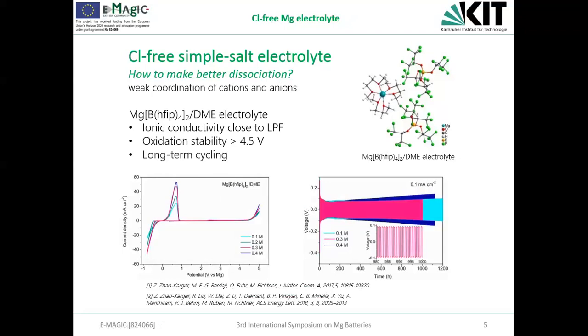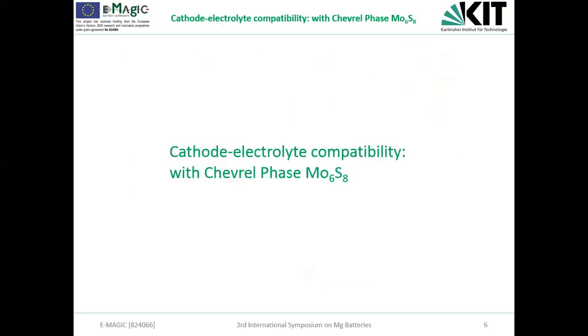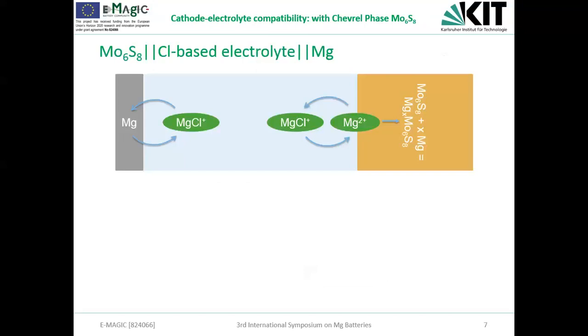In the symmetric cell, we could run it for more than 1,000 cycles, and we didn't observe an obvious increase of the plating and stripping overpotentials. So with a nice electrolyte solution, we move one step forward. We checked the compatibility between the electrolyte and different cathodes, just to check whether it is as we expected. The first electrode, or the cathode we tried, is the benchmark cathode, the Chevrel phase. And what I want to mention here is that the combination of the Chevrel phase with a chloride-free electrolyte system is not straightforward because